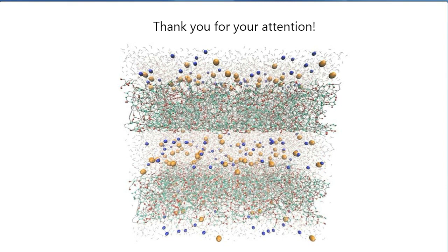In this work with the simulation and the charging, do you see an optimal pore size for chlorine versus sodium? So the carbon atoms were fixed in position for the work I showed today — the electrode cannot breathe. We could see the chlorine ion getting to the pore faster in time than sodium ion, because the hydration shell stability of sodium is larger than that of chlorine ions. Clearly, chlorine ions are bigger ions and they diffuse within maybe one nanometer from the outside surface, while sodium ions can probe more of the porosity. That's the picture with frozen atoms.